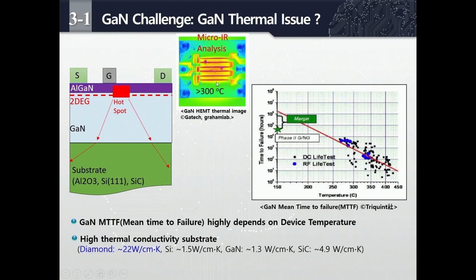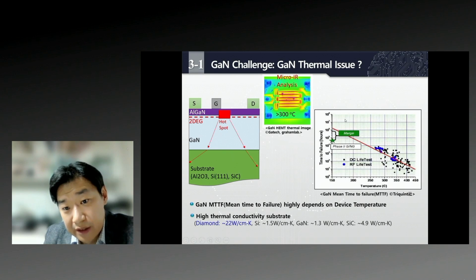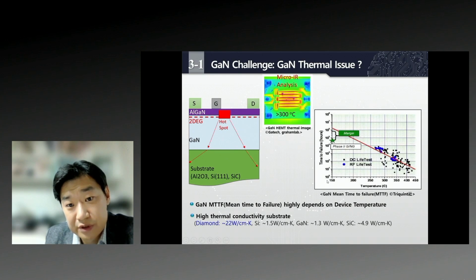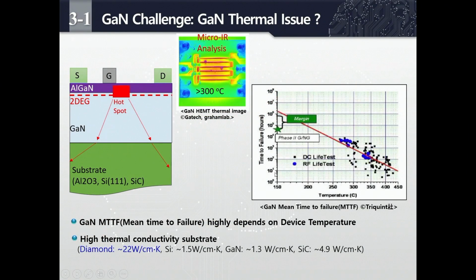So what happens when we increase the junction temperature to more than 300 degrees Celsius? We can look at the graph. At a typical junction temperature of less than 150 degrees Celsius, the lifetime is 10^6 hours. But when we increase the junction temperature, the lifetime dramatically decreases, to 10^3 hours. So lifetime is strongly influenced by the junction temperature.